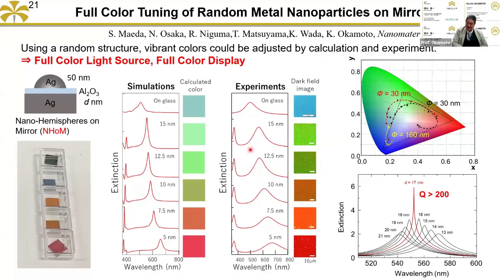So it depends on the material. In the aluminum case, aluminum is not so stable, but it makes an oxide layer, and then it becomes stable. But in the silver case, the interface of the semiconductor and the silver is okay, but the other side, silver is not so stable. That's also important. That's why sometimes a protection layer is necessary on the silver. But for light enhancement, the protection is okay, since surface coupling is not there.